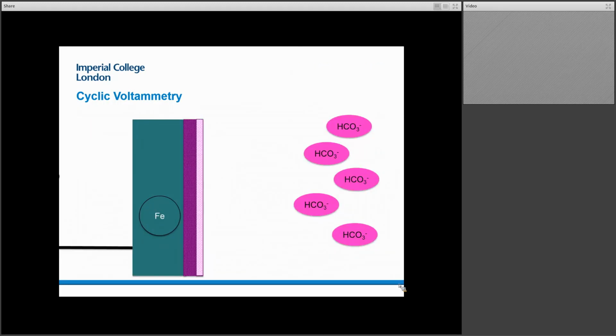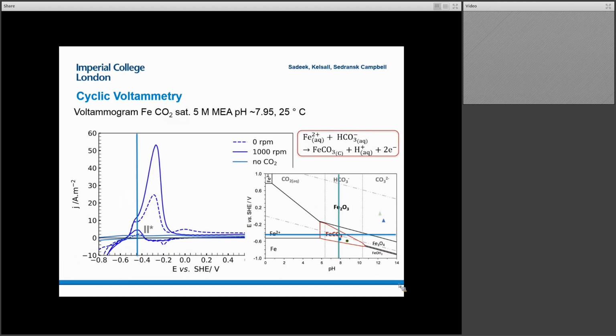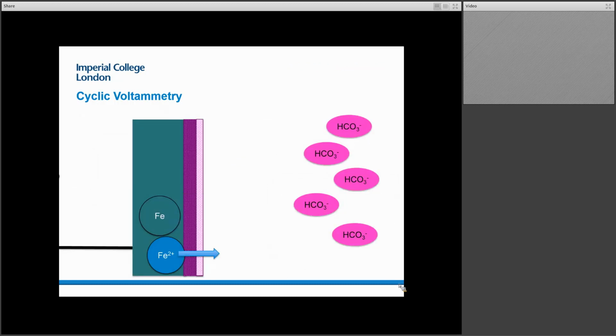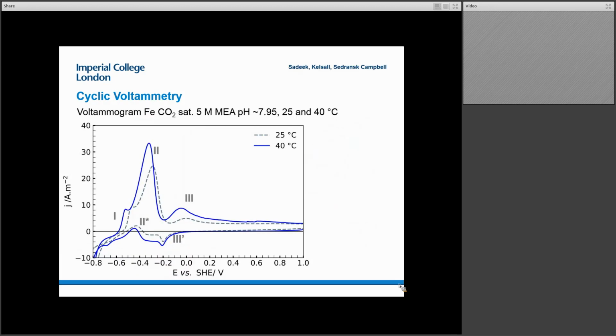But it becomes even more interesting because we believe that by doing this, we're changing the nature of that film, certainly on the outside, but perhaps even the inner film at this point, due to those reduction reactions. And so porosity may likely be induced, because one of the unusual things here, as I said, is that we have a net current. But we are seeing overall oxidation, so we're having reformation potentially of iron carbonate in a very unusual place. But again, as a function of all these different parameters, we can actually highlight when we make it and when we don't. And now we suspect, and in fact this is possible due to ion transport through basically what we've created, a somewhat porous layer.